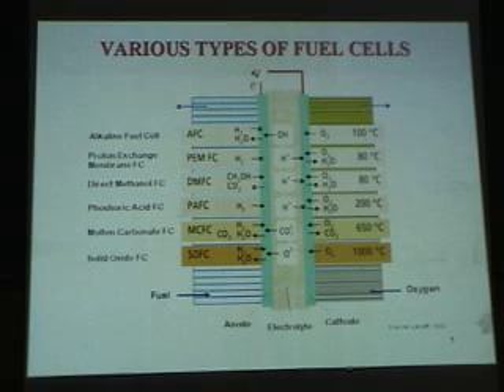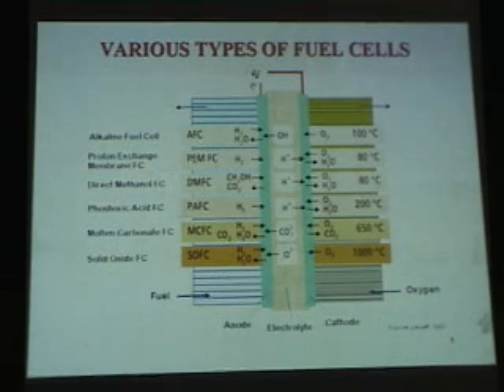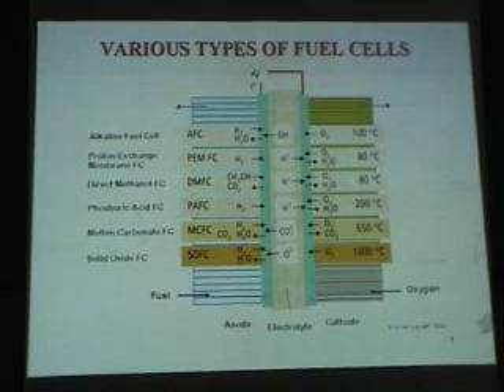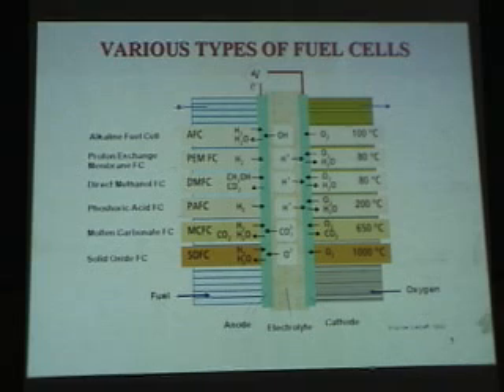Now, if I have to bring it to $300, either I should bring down the cost of the electrode material that we use or the cost of the membrane. But at the moment the membrane is a monopoly item, more or less controlled by DuPont's Nafion. Therefore, unless somebody comes up with a new membrane, it is not going to be easier. Whereas the loading of the platinum can be reduced. But the point is the loading of the platinum has to be reduced from 3 milligrams to 0.01 milligram, while keeping the efficiency of the process the same as at 3 milligrams per square centimeter. That is the logic which we are using.